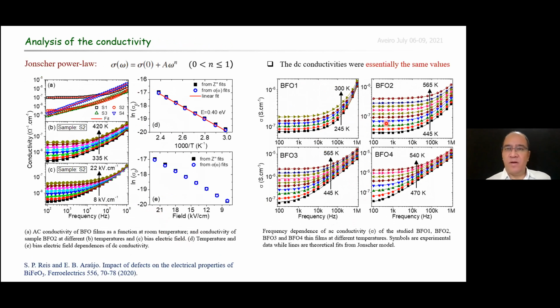Additional analysis on AC conductivity for all studied BFO films was conducted using the jonscher power law model. The DC conductivities obtained from fitting these curves were essentially the same as those obtained for grain boundaries from impedance and electric modulus spectroscopy.